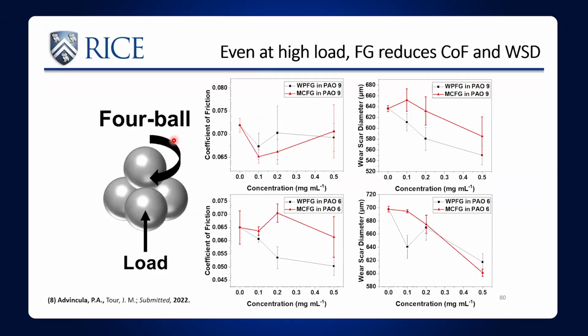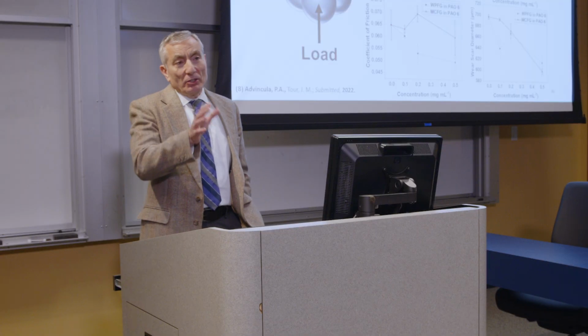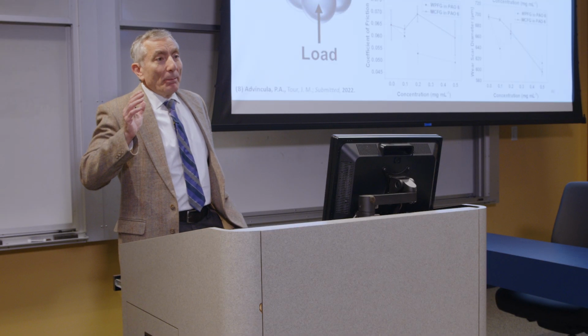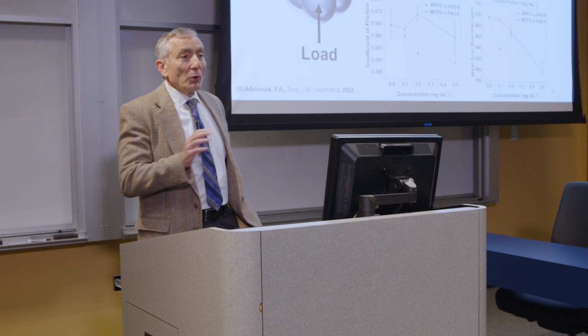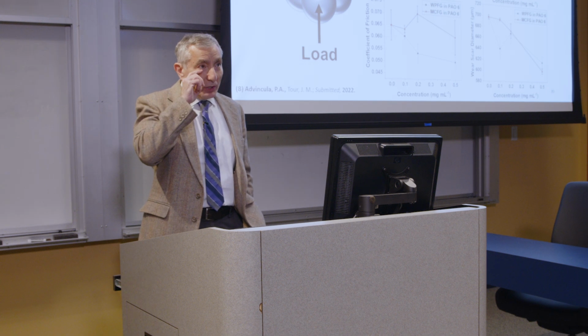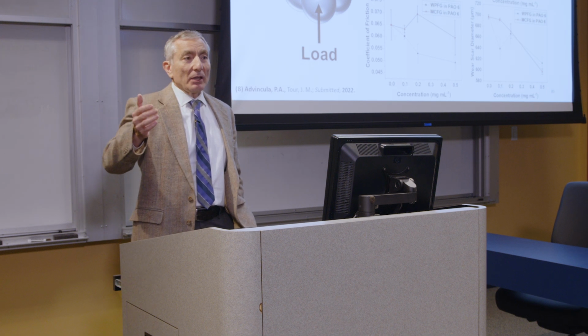We've also used it to reduce friction. So what happens if we can take these sheets and we can mix them in with different lubricants? In this case, this was just polyalpha olefin 9, a typical lubricant. And what you can see is the coefficient of friction reducing as you add this in. This is huge. I mean, to you, lubricants, who cares? But lubricants in your car are so important, because if you can reduce friction, that's better mileage.